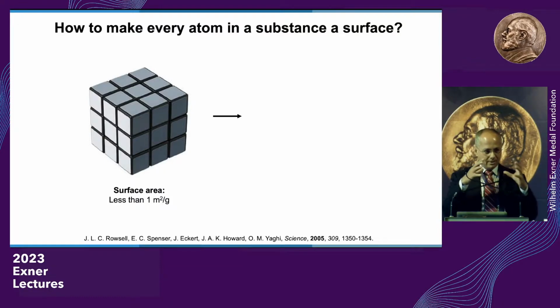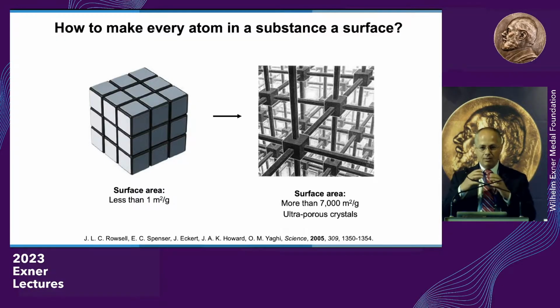So we opened up the structure. When you open up the structure, you get a surface area of 7,000 meters square per gram. Okay, you make an ultra-porous structure. Why? Because now when you open up the structure using the building block chemistry I just described, you make every atom in that structure an adsorptive site.